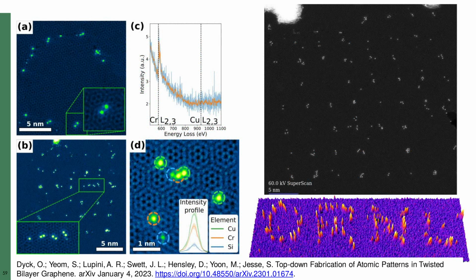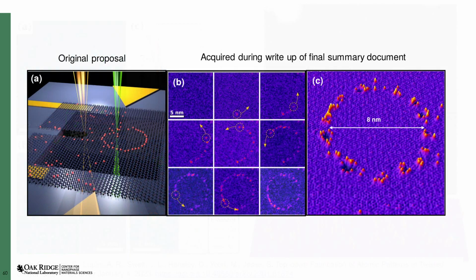clusters into the twisted bilayer graphene. Unlike the initial demonstrations of atomic insertion, where we had to be very close to the parent nanoparticles, we can now pattern wherever we like in arbitrary patterns. But it turns out most of the inserted atoms were not chrome like we thought they would be. Instead, they were copper atoms.